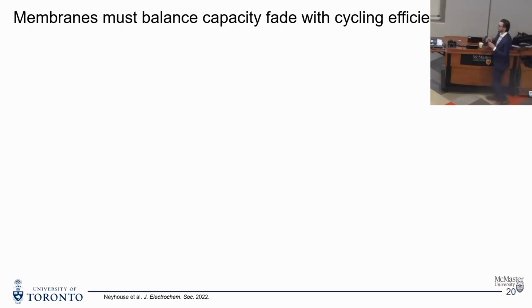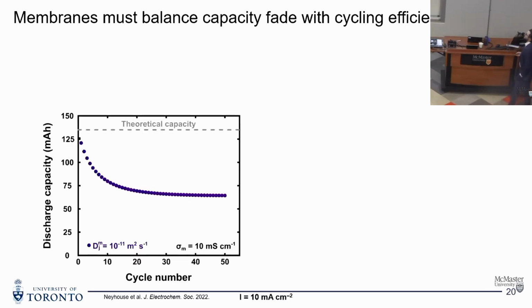Now, one thing I want to focus in on specifically that we use this for was to look at membrane performance. And this is going to talk a little bit to some of the experimental work I've done. So I talked about membranes balancing crossover, in the form of capacity fade, with their energy efficiency or cycling efficiency. And so the other thing we care about is not just efficiency, but lifetime. So we care about how the capacity, basically our ability to store charge, changes over the course of cycling, going from 0 cycles to 50 cycles. And really, it's this time-dependent characteristic that we care about when we're using this more computationally fast model.